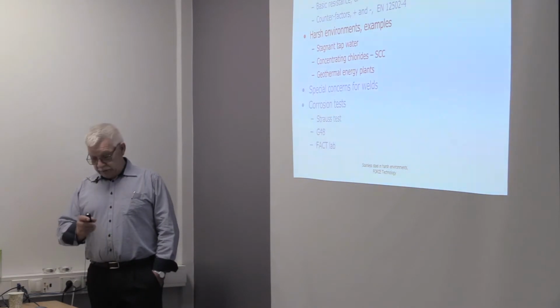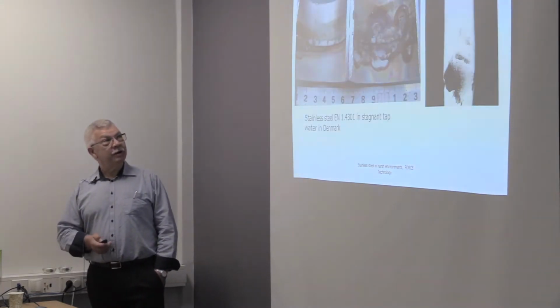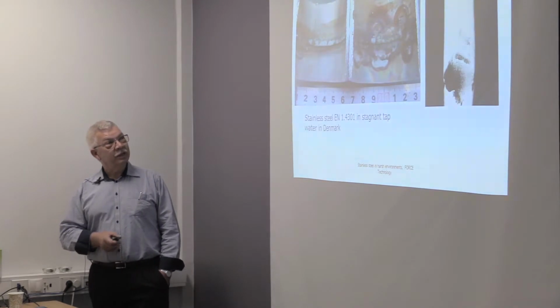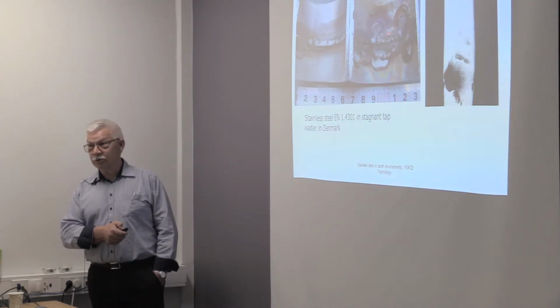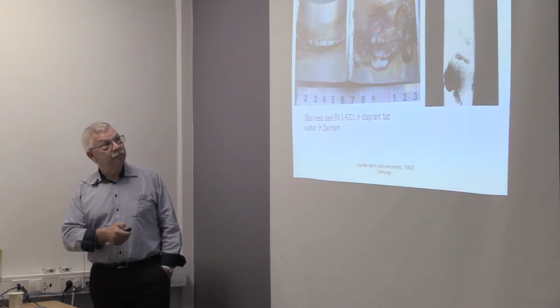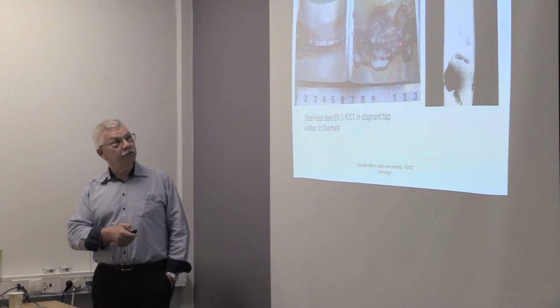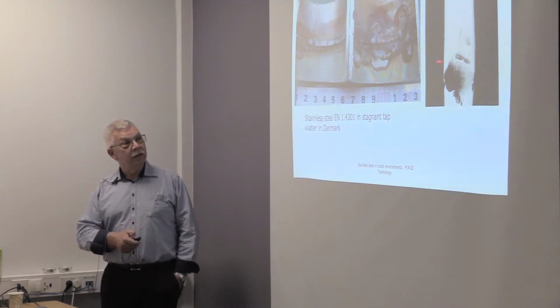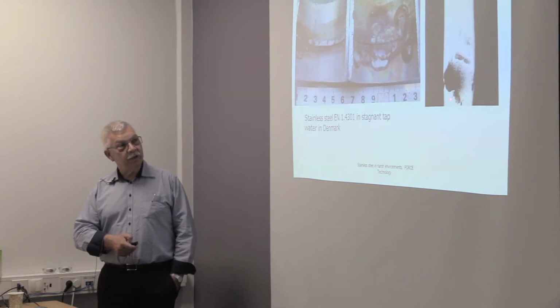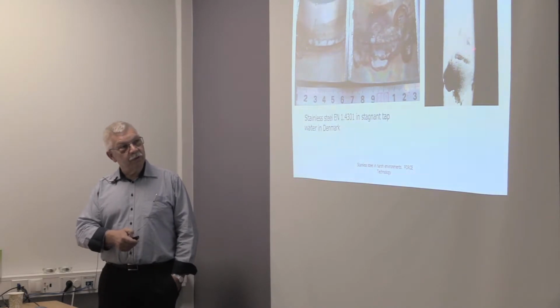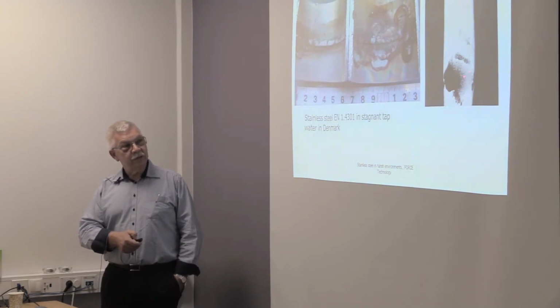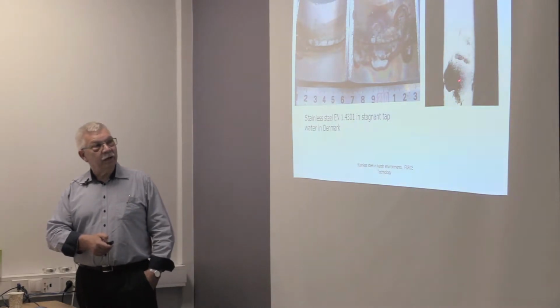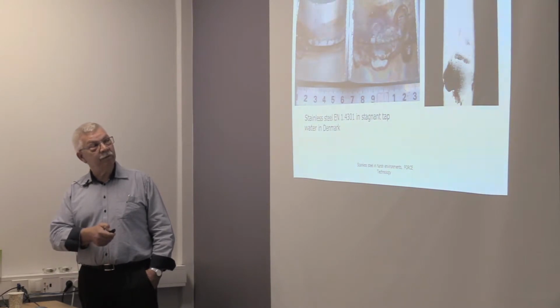And on to some examples of harsh environments. And this, the stainless steel says this was too harsh. You can see we have pitting corrosion, we have a lot of rust formation around this weld. And in a cross section you can see how this small hole in the surface is growing into a big cavity, and the weld metal is like a sponge due to corrosion. And we even have a pitting here, which is in the heated oxidized zone.